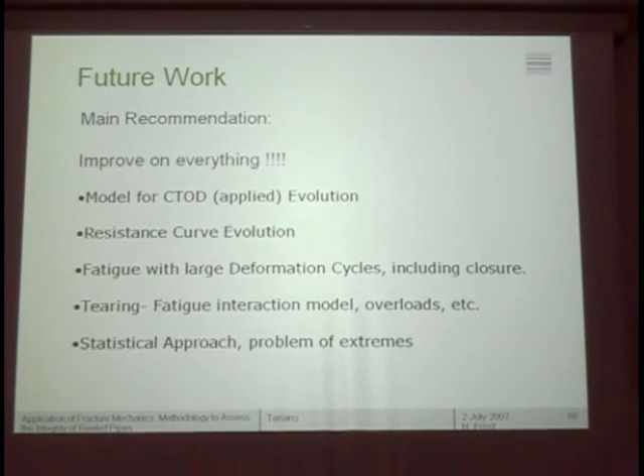The business of resistance curve evolution, if you start including tearing with fatigue, one very high cycle and then another smaller cycle and so on, you start getting into overload effects, which were not taken into account in a way by this approach. We didn't take that into account in the fatigue, obviously, nor in the resistance evolution. So fatigue with large deformation cycles including closure also needs a better understanding, particularly when the cycles are so big and the amount of crack extension is also so big for these cases.